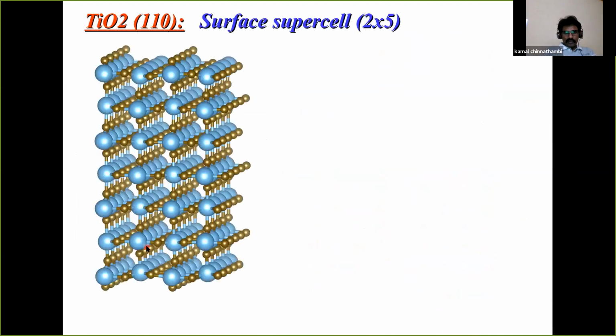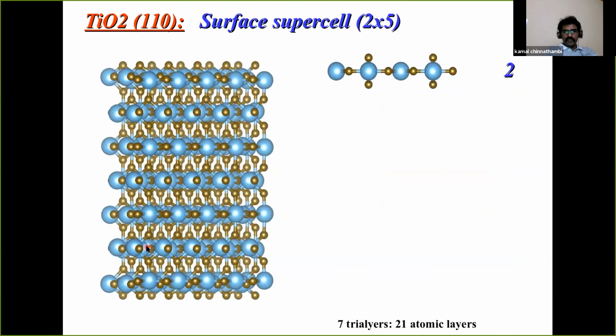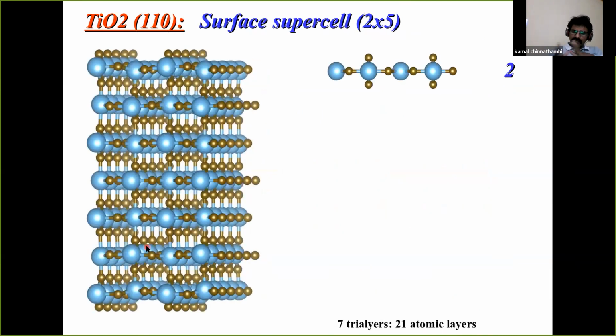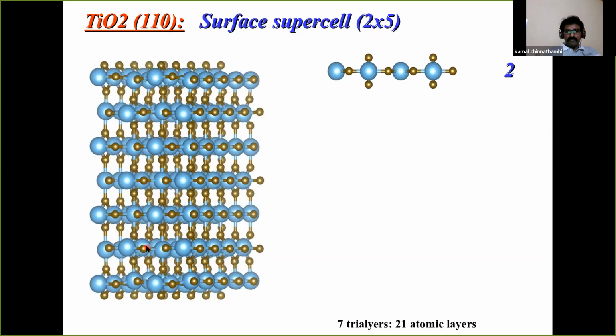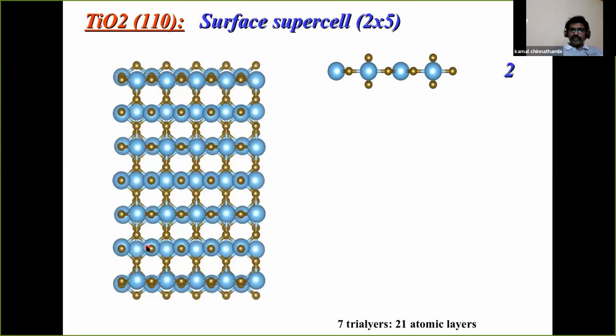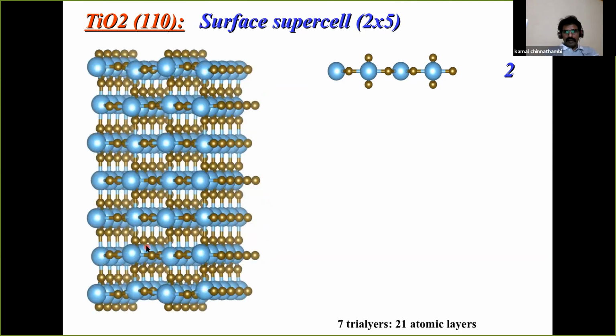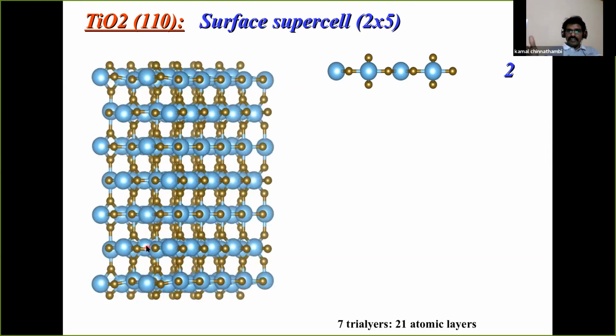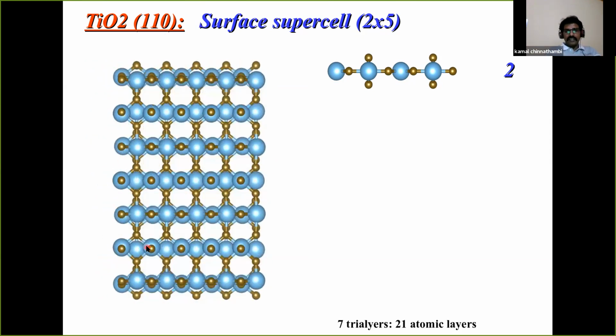Before going to that, I want to briefly mention what this surface is. So the titanium oxide 110 surface looks like that. This slab contains 7 tri-layers of titanium oxide, so it contains 21 atomic layers. Whenever you create a surface, the surface unit cell can be different from the bulk unit cell. In order to define the surface unit cell, you need 2 parameters: one is the length and the other is the breadth, if the angles are 90 degrees.